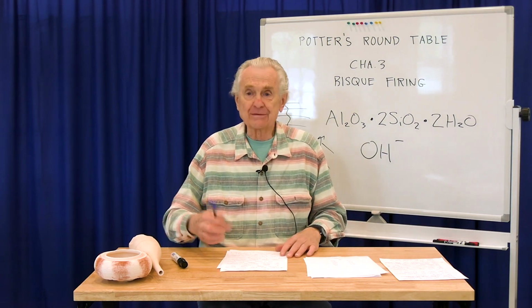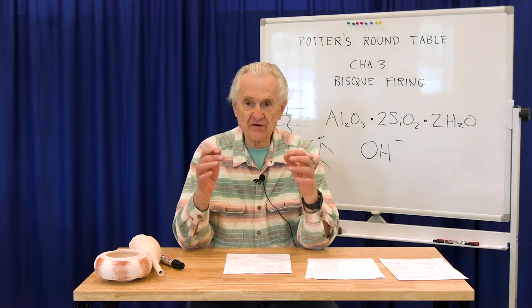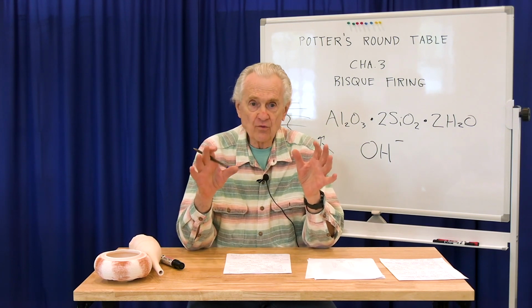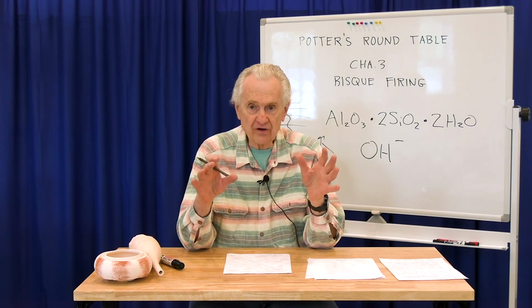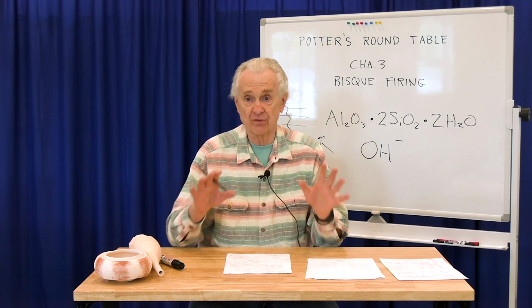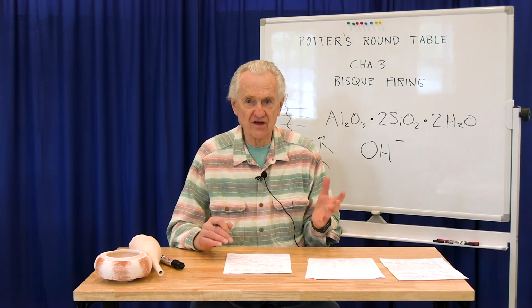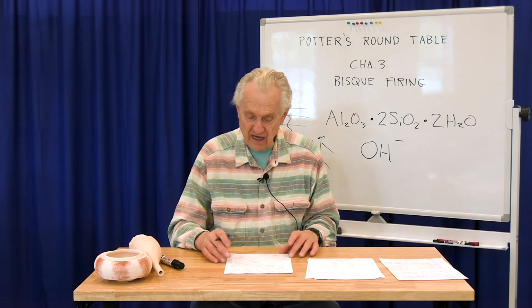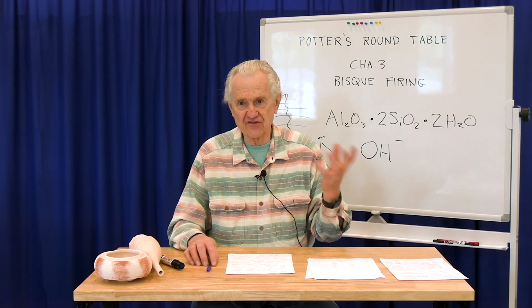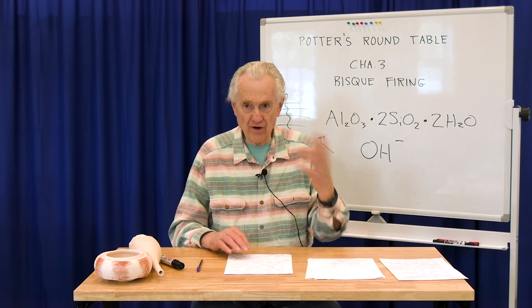Okay, well, why does this matter? Well, it matters because it means that, as I mentioned earlier, bisque firing must provide enough temperature and time for all this to happen. And one of the things that's important about this is very early in the firing, the temperature has to be controlled very precisely to avoid steam explosions. The problem is when you have liquid water present, meaning, for instance, you may think the pots are dry, but they're not completely dry. If the water is heated up too quickly and it turns to steam, it expands violently, where it can actually blow up the pots.